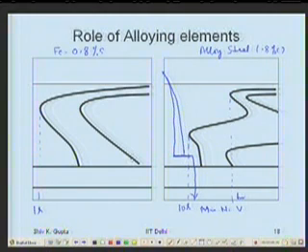Further, that I also can do. So why do I have enough time here? I'm able to cool it such that I do not cross this or do not cross that. Okay? I have equilibrated my temperature and then I can quench it. So the exterior and interior are trying to transform simultaneously. It's not happening that the surface becomes martensite, interior is still soft austenite. Alright? So this is what the alloying additions are doing.